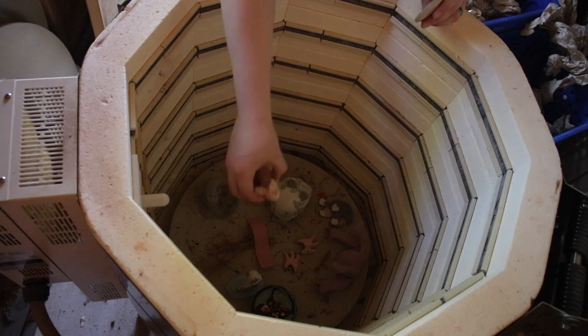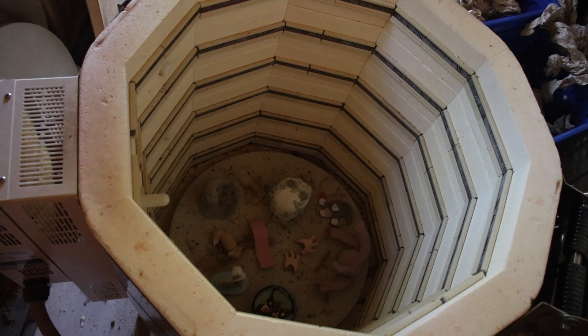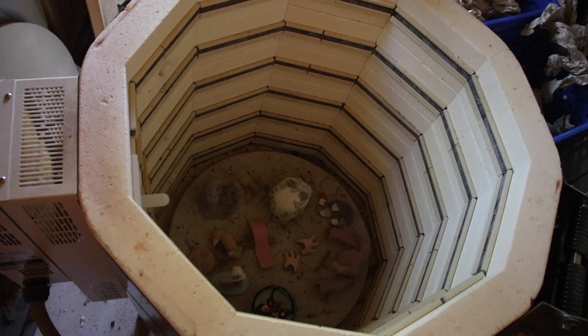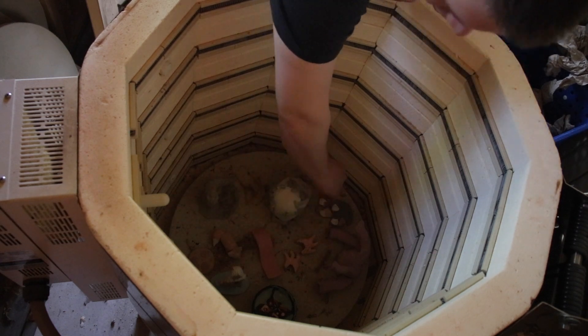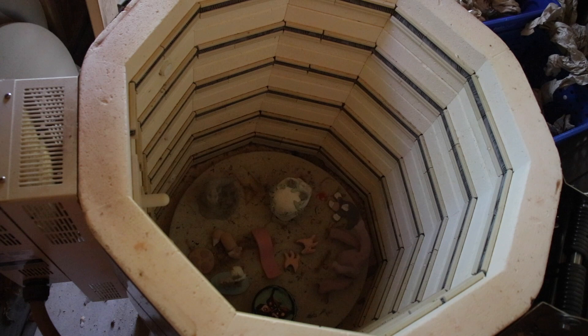While I'm sitting in these projects, the glaze, when it's inside, becomes red hot and sticky. So I want to make sure that none of the projects are touching each other. I also want to leave enough space around each project for airflow to go around, to make sure all the projects heat up evenly and all the glaze is the same shade all the way around. If one side is too hot and one side is too cold, they may turn out slightly different shades.